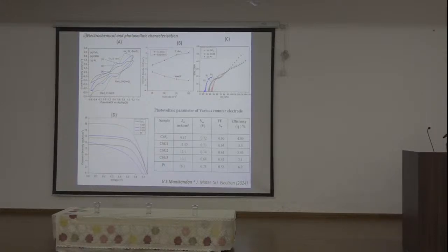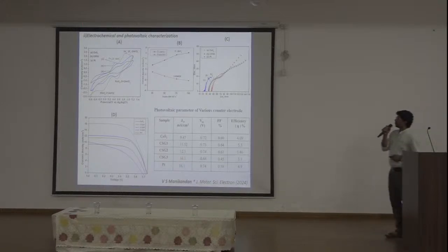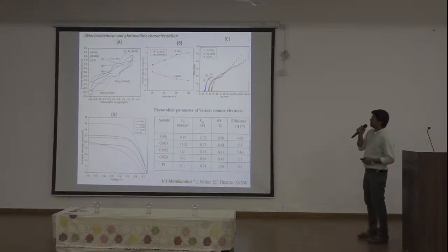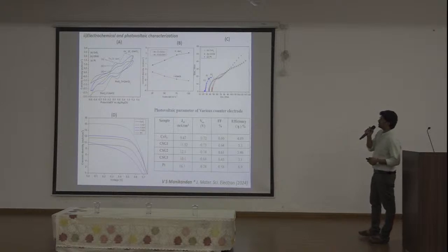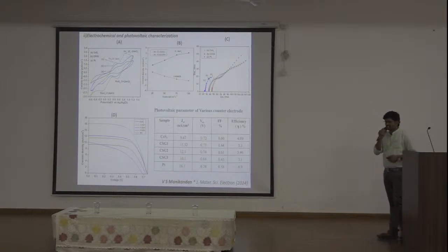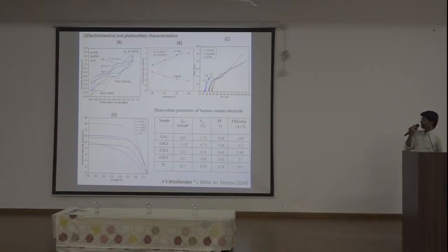So it is showing the higher electrocatalytic activities. After that, we can see the cobalt sulfide has a lower current density. After inclusion of reduced graphene oxide, the charge current density is increasing because the RGO is providing more active sites to interact with the electrolyte, improving the charge current density.